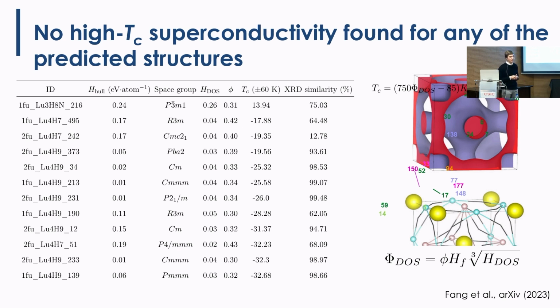Okay? So in all these crystal structure predictions for lutetium, hydrogen, nitrogen compounds, we calculated the critical temperature with this very fast estimator. Okay, the maximum we got was 13 Kelvin. Nothing. So basically, we believe there is no superconductivity in all the structures, stable and metastable, in a range that we consider reasonable for metastability. Nothing. And this is consistent with other people. Many people have done crystal structure predictions, also including nitrogen, so nobody finds anything that can be a high-temperature superconductor.